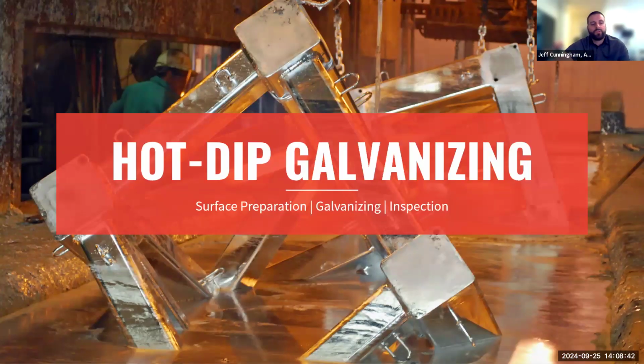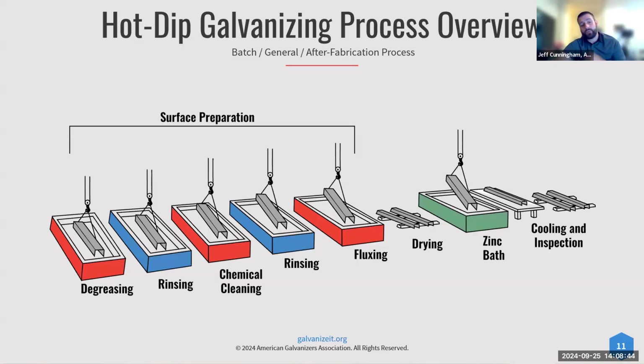All right, so next we'll talk a little bit about the actual galvanizing process. This is just kind of an overview. The galvanizing process starts with surface preparation, which is absolutely critical because the part has to be clean in order for the iron and the zinc to react and form that metallurgically bonded coating. If you just dipped a random piece of steel you found without cleaning it, you're going to have a lot of bare spots because the zinc and the iron won't react. So that's why it goes through a series of surface preparation steps.